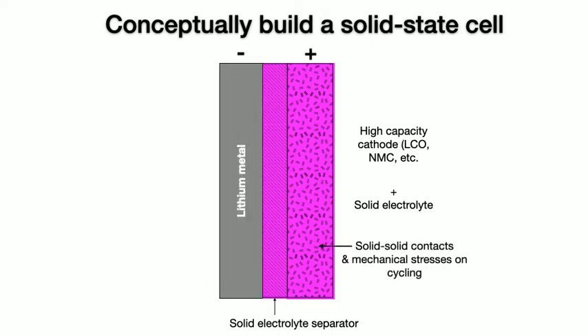Well, in the cathode, you have a large number of solid contacts and interfaces, and those have to be maintained with cycling. So, when you cycle, there are volumetric changes that introduce mechanical stresses that can cause disconnection of those interfaces, and that would be manifested as a resistance rise and loss of capacity.